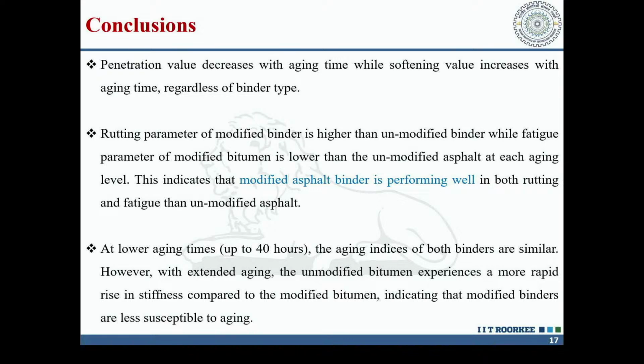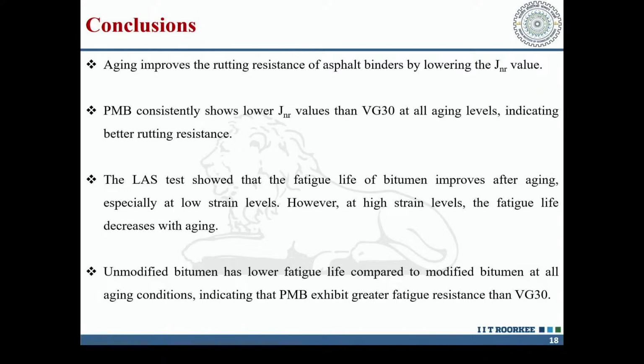So this is showing you the conclusions that the penetration value is decreasing with aging time, while softening value increases with aging time regardless of binder type. The rutting factor is increasing with aging, and the fatigue factor is also increasing. This is there in this case also. The PMB consistently shows better JNR values than VG30 at all aging levels, indicating better rutting resistance, and the LAS test, which was also done, showed that the fatigue life of bitumen improves after aging.